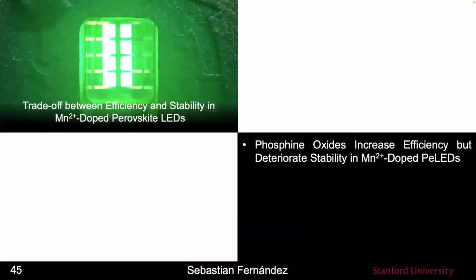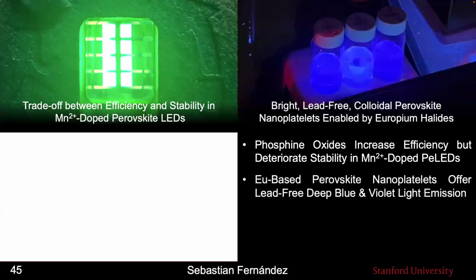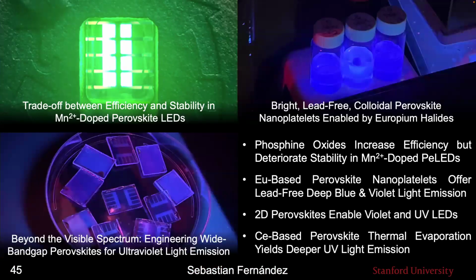And so to briefly conclude, we looked at how we can improve the efficiency of these perovskite LEDs with manganese dopants, but unfortunately comes at a cost of stability using these phosphine oxides. How these europium-based pure lead-free perovskite nanoplatelets offer lead-free deep blue and violet light emission, and additionally how 2D emissive perovskites can enable violet and ultraviolet LEDs, and how the thermal evaporation of cerium-based perovskites can really move us more forward into the ultraviolet spectrum.